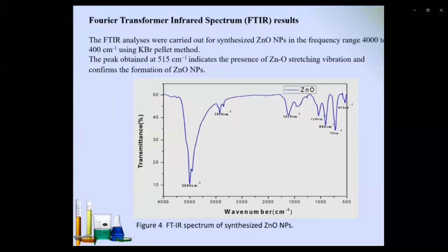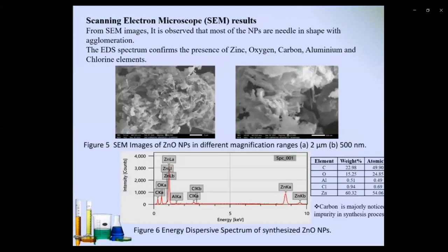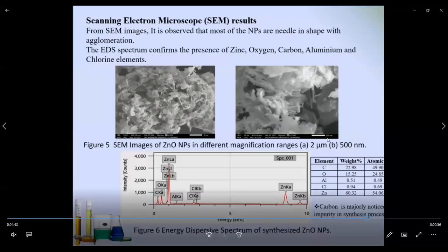The very next one is the Fourier transform infrared spectrum here. From this spectrum, we can observe that different functional groups are present in synthesized nanoparticles, and exactly at the peak 515 per centimeter indicates the presence of zinc oxide stretching vibration and confirms the formation of zinc oxide nanoparticles. From scanning electron microscope result, we can observe here that most of the synthesized nanoparticles are needle in shape with agglomeration. And along with that, EDS spectrum confirms the presence of different elemental composition. So here we can notice that zinc, oxygen, carbon, aluminium, and chlorine elements are present in the synthesized nanoparticles.